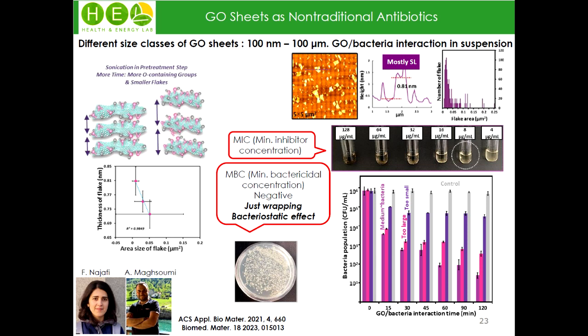This was in suspension form, because we developed a suspension, not like wound dressing or immobilized graphene oxide. Using minimum inhibitory concentration and minimum bactericidal concentration measurements, we found that the mechanism is just wrapping and isolating the bacteria, so it has a bacteriostatic effect instead of a bactericidal effect.